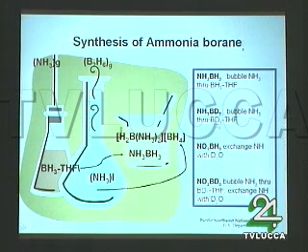And fortunately, you can buy deuterated borane THF and do the same process and get deuterium on your boron. You can put the deuterium on the nitrogen just by exchange, since it's very labile. You can exchange it with D2O washes, do that a few times and wash all the hydrogen out. And then the last one that we really want, the per-deuterated one, is just to start with the deuterated borane THF and then exchange that. So we have all four of these samples now so that we can go through and see what the reactivity of these things is. We need these for fingerprints for control experiments, but we're going to make an intimate mixture again of the ammonia borane and the per-deuterated species.